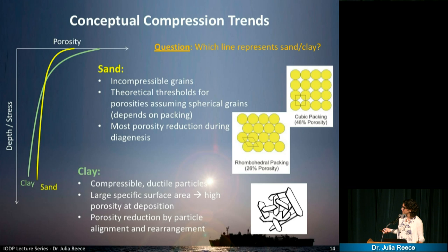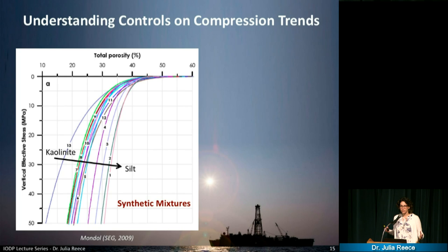And so we try to figure out, well, what is it really that controls what we call compression trends? There are some groups that have tried to study it in a very systematic way. They have taken a clay mineral that is a kaolinite and then mixed that with some silt, which is quartz, just a little bit in a finer size. And you can see that there are some systematic trends here, but is it really so representative if you just take two minerals and mix them together?